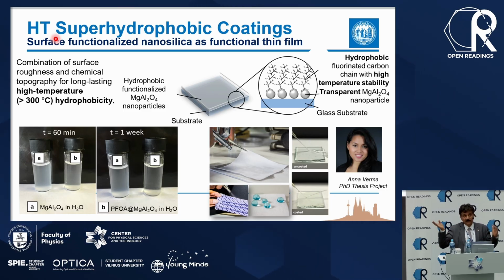A lot of chemicals go. So if you can somehow inhibit the nucleation of ice crystals, you can save a lot of energy. So there is a big interest in this high temperature hydrophobic. Please remember this high temperature. Room temperature hydrophobicity you can do with any organic. You can take a parylene coater, you can take a silane, and you have a hydrophobic surface. Hydrophobicity is stable at higher temperature. So that's why I'm saying 300 degrees is a world record. So we were very happy to have this.